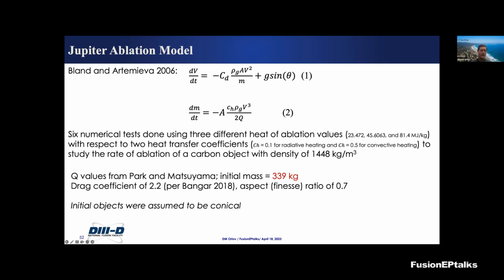He was using the Q values from the models I mentioned before, Park's and Matsuyama's models. He took the initial mass of the meteoroid of about 339 kilograms, used a drag coefficient of 2.2 in the equation of motion, and assumed the initial objects to be conical in shape, similar to maybe the Galileo probe, because he wanted to make parallels between the Galileo probe and our studies in the DIII-D tokamak and the meteoroid ablation in the atmospheres.